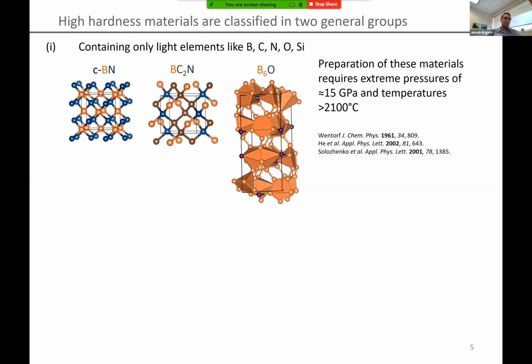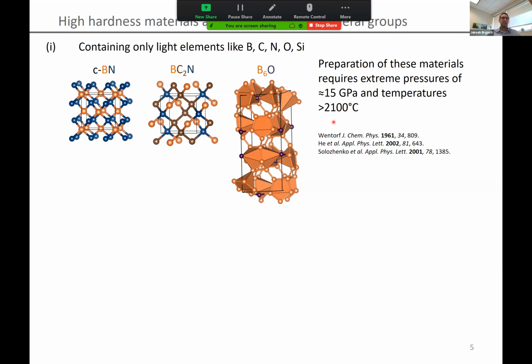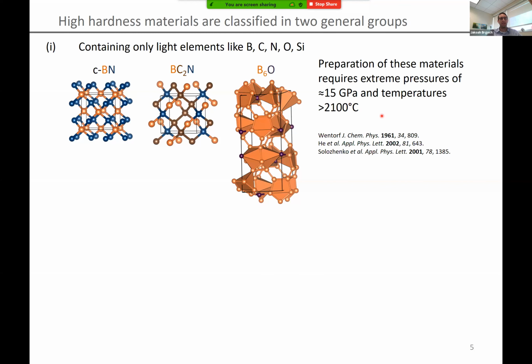Now, the synthesis of super hard materials is possible in an industrial setting, but they require extremely high pressures, 15 gigapascals, and more than 2100 degrees Celsius. And the really big issue here is the fact that the pressure and temperature of 15 gigapascals and 2100 degrees Celsius need to be applied concurrently. This is effectively a bomb that you need to make these high pressure phases. And these are not easy synthetic conditions, but as I said, industry has found ways.